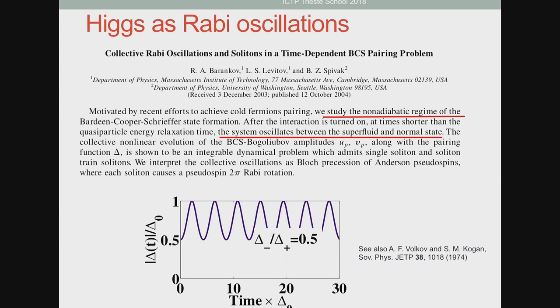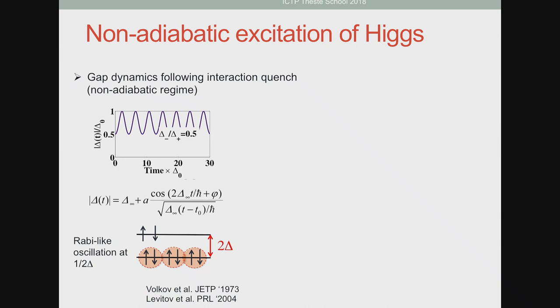They essentially non-adiabatically changed the pairing interaction. And what they see is an oscillation. The system oscillates between the superfluid and the normal state, that's what they say. They see an oscillation of the order parameter, and the inverse of its period is exactly 2 delta. It's the gap. So it's, if you want, the analog of the Higgs mode I just described, but this time not in the frequency domain, but in the time domain. So in the non-adiabatic regime, you can have access to these dynamics.